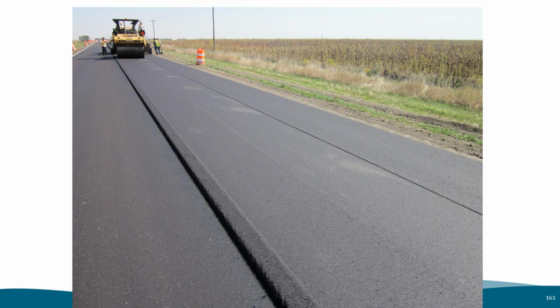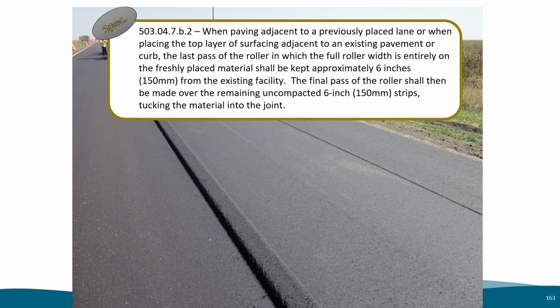Here is the exact way that a joint should be compacted. As written in the standard specifications, when paving adjacent to the previously placed lane, or when placing the top layer of surfacing adjacent to the existing pavement or curb, the last pass of the roller, which is the full roller width, is entirely on the freshly placed material, shall be kept approximately 6 inches from the existing facility. The final pass of the roller shall then be made over the remaining uncompacted 6-inch strip, tucking the material into the joint.